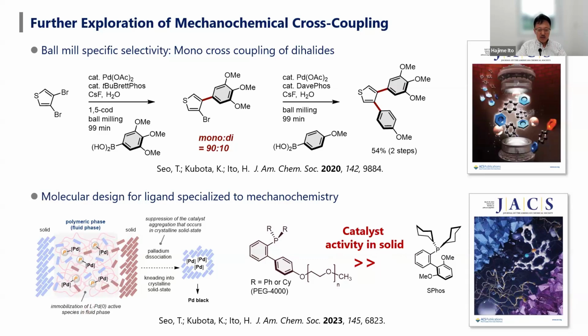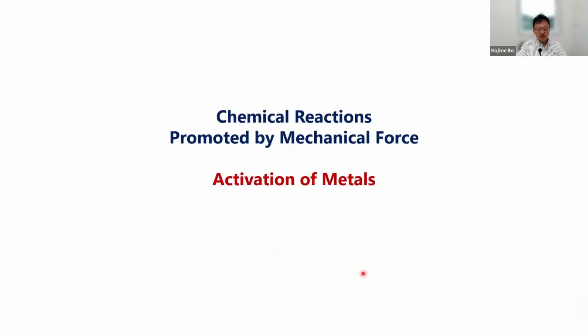So for cross-coupling reactions, maybe the major role of ball milling mixing is just high mixing efficiency. But we tried to find another possibility for ball milling reaction conditions by using the mechanical force generated in the ball mill jar.